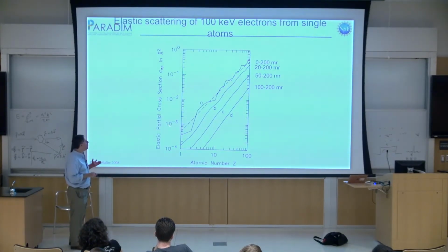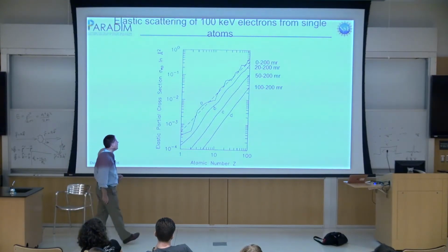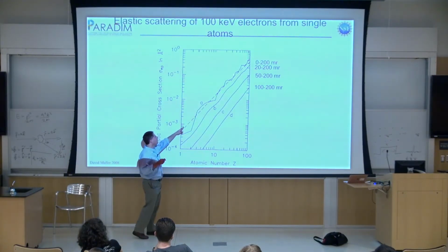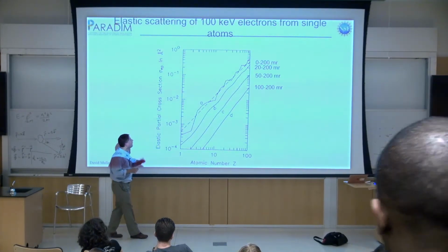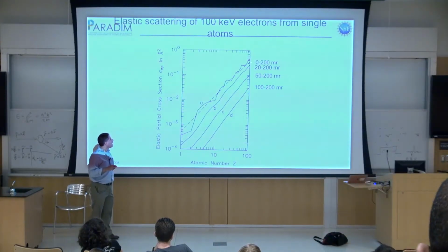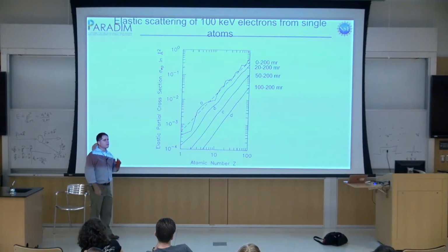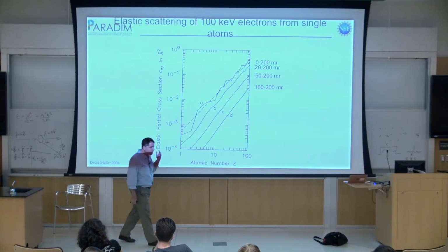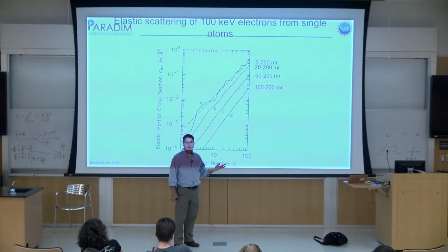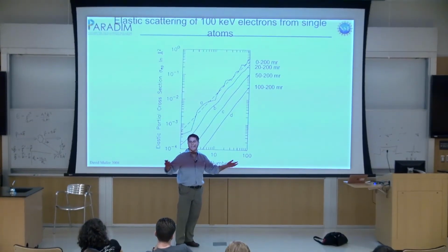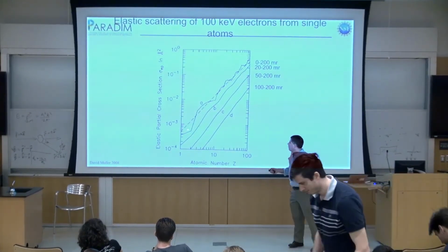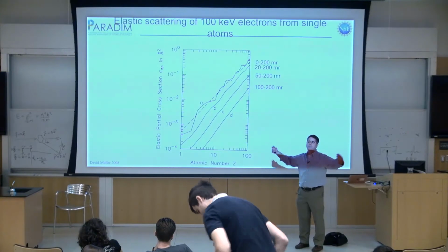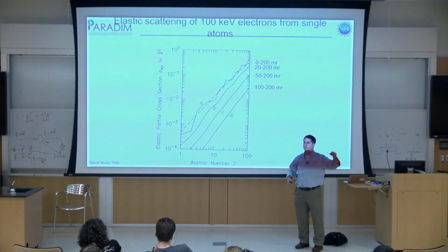If I look at the total scattering or the forward scattering, it's a lot more signal, but it doesn't vary smoothly with atomic number. What's happening is it's zigging and zagging because with the small angle scattering, you're measuring the mean inner potential of the sample, and that's basically the size of the atom. And if you remember your periodic table, as I go across the periodic table, the atoms shrink in size, and then you go back to the next row and they get big and fat again.